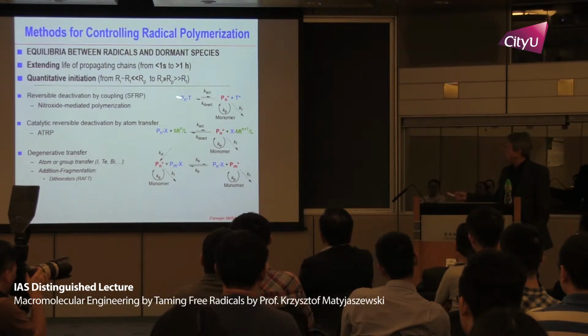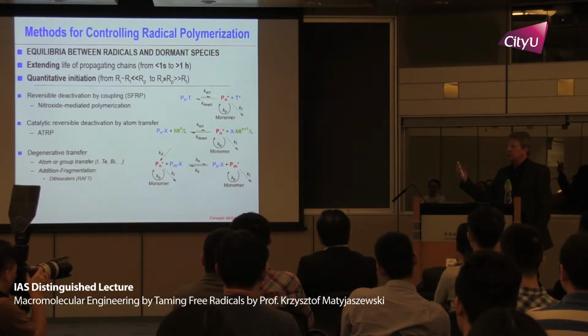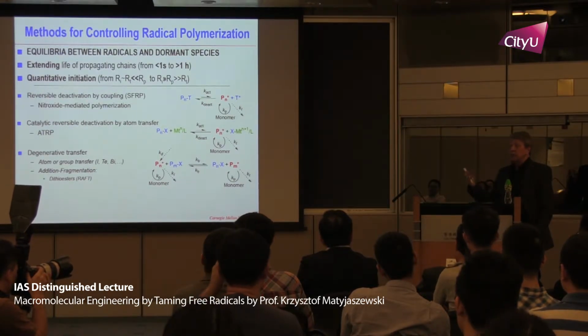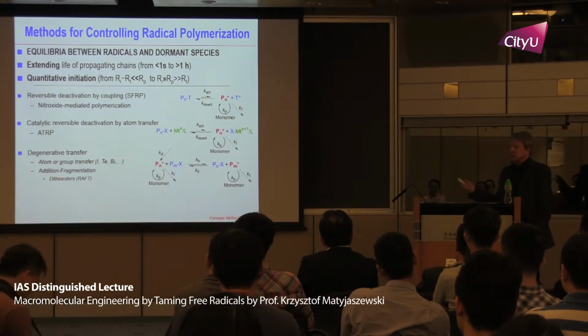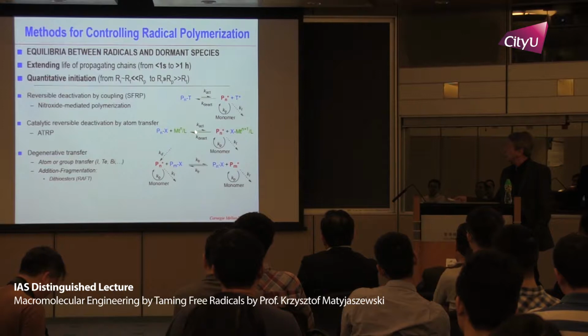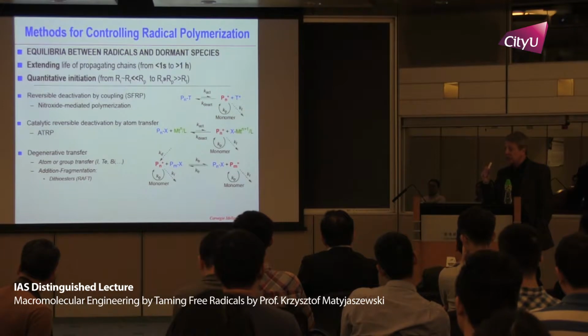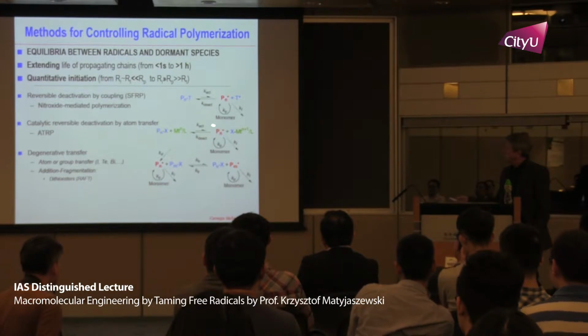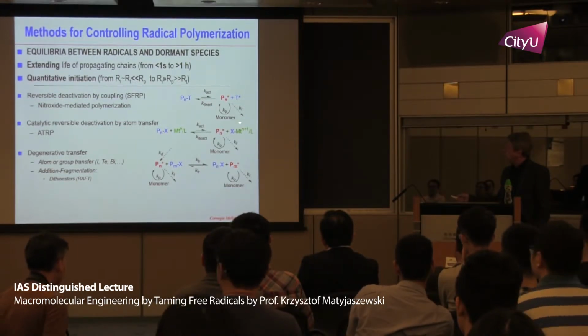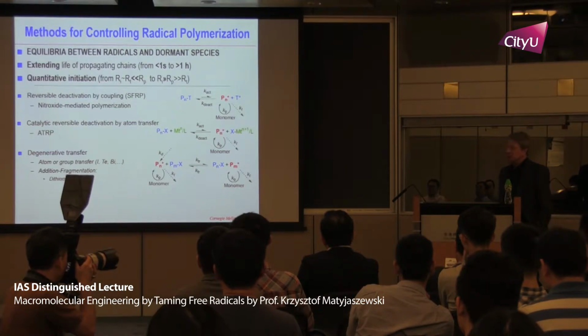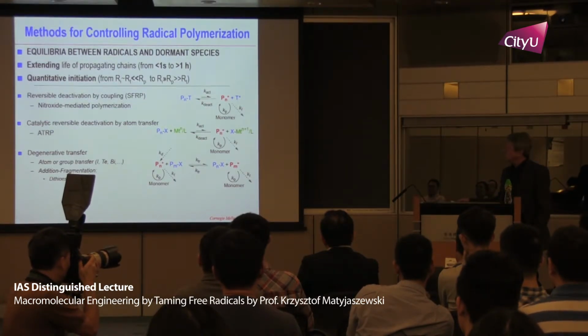in that case, the bond is so strong that you need to heat it to 300 degrees to have it labile enough. So what can be done in order to reduce activation energy from 70 to maybe 10 kilocalories per mole? You can use catalysis. This catalytic system, as I mentioned to you before, is very special, meaning that you have two forms of catalyst: activator, which would generate radicals, and also deactivator, which puts it back to a dormant state. Without activator, there would be no polymerization. Without deactivator, it will be uncontrolled radical polymerization.